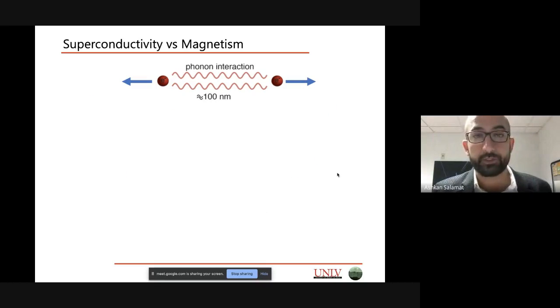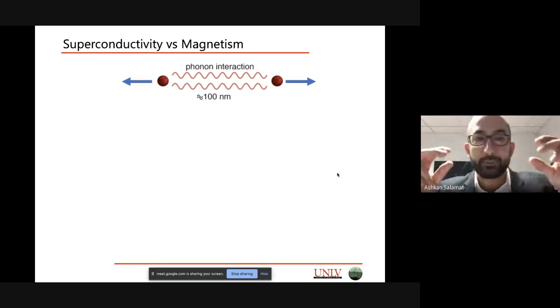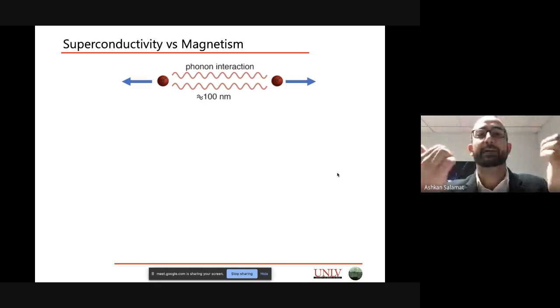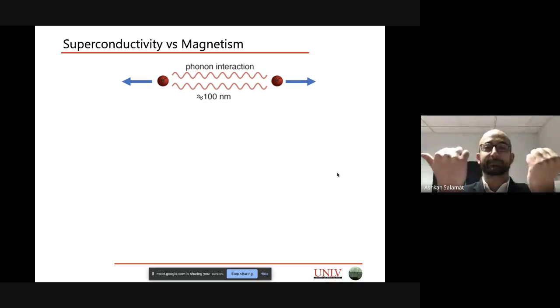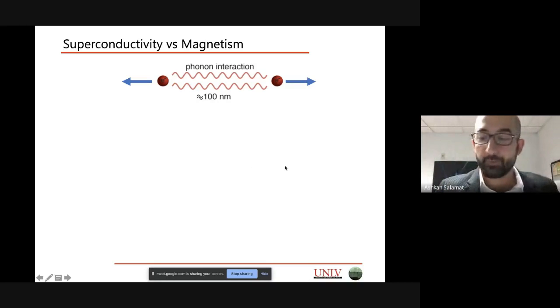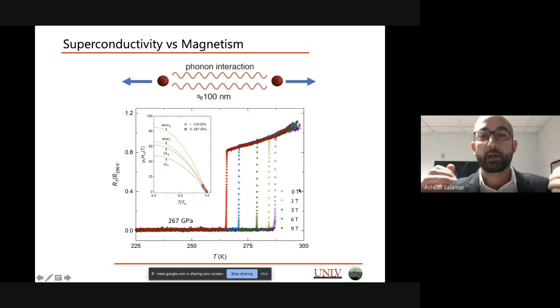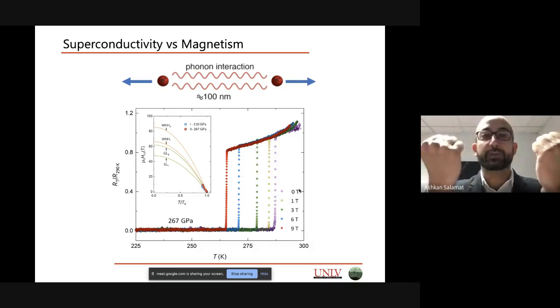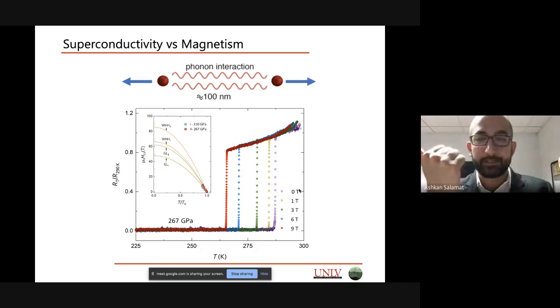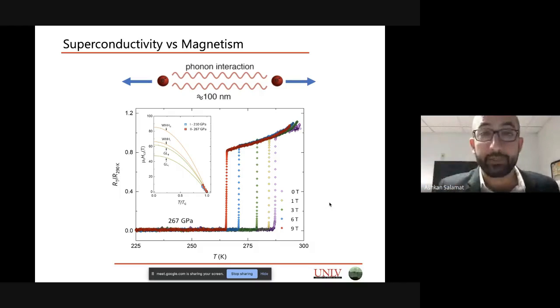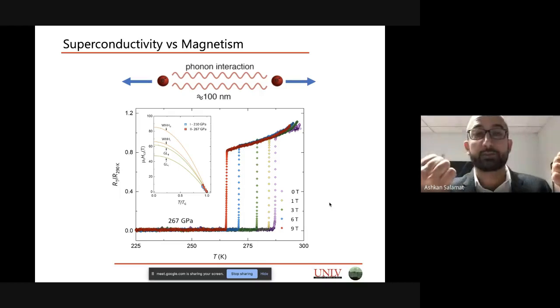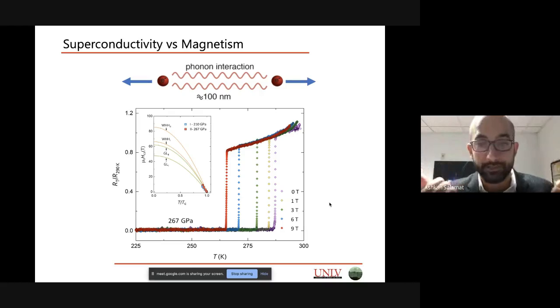Also, what's important, just again for my few fellow physicists, is these Cooper pairs, these electrons that are entangled in energy space to each other, actually have opposite momentum vectors, whatever that might mean. And what we're able to do is we can apply a magnetic field, and the magnetic field generates a force between these two electrons that breaks the superconducting state. And so as you increase the magnetic field, you can disrupt the superconducting state, and you can lower the superconducting transition. And that's exactly what we're able to demonstrate.